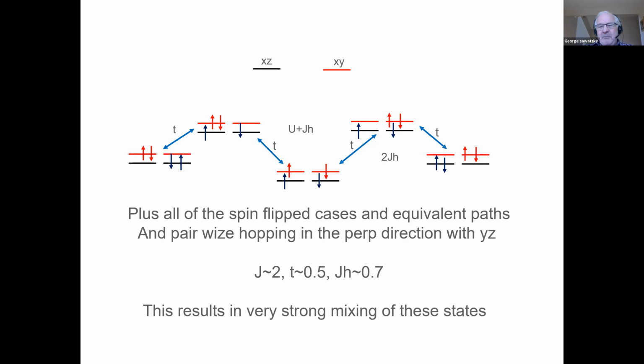But I really feel that because of these degeneracies, you're going to have a Jahn-Teller problem. And I think that because of that, it will want to do something. And the one thing it could do is indeed orbitally order and give you the nematic type of phase, also as far as the lattice is concerned. And it could even do that before it does the magnetism, because it's so strongly coupled to the lattice. And this picture, by the way, would be an electron-phonon coupling, where the coupling is in the hopping integral, not in the on-site energy.